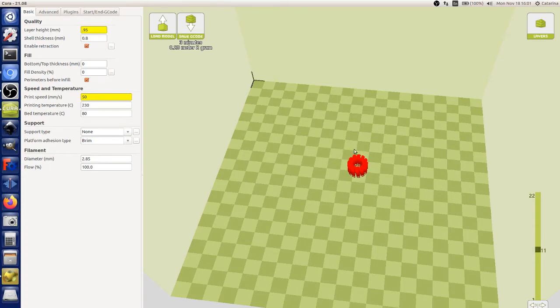There's a feature you have to pay attention to, and that is getting the bed too hot. What we've noticed is, you can print at, say, 60 C or 80 C. That's what we've been doing here. 60 or 80 C for the print bed on our printer. But if you get it up higher, like 100, it'll be so hot that the bottom layer is still kind of molten that the print will simply not stick. So for the bed temperature, you also want to have an optimal temperature. It can't be too hot because the print won't stick to it.